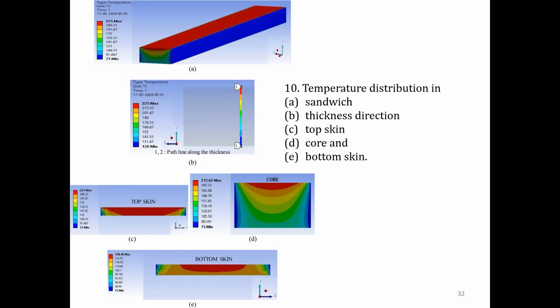Cyclic cooling and heating of the extruded metal can be seen as the temperature distribution is minimum at the bottom and maximum at the top layer, naturally because of sequential consolidation, sequential cooling. And as the heat gets conducted between the layers, the bottom layers are cooled and heated cyclically. The highest temperature, needless to say, is to be noted for the just deposited layer, whereas the side faces of the sandwiches are cooling at a faster rate due to convection.